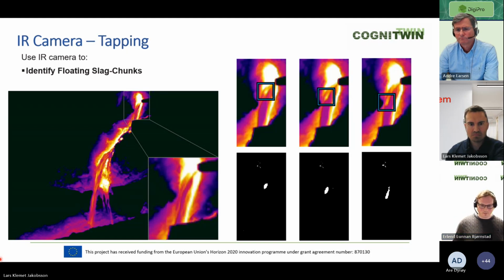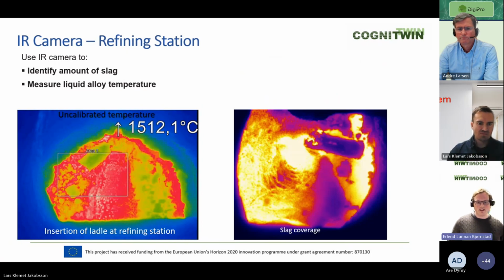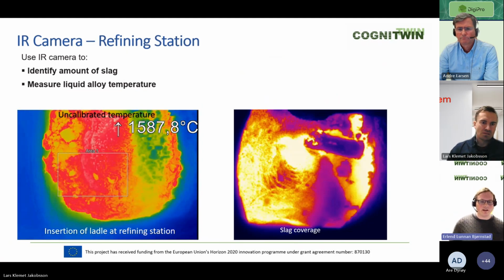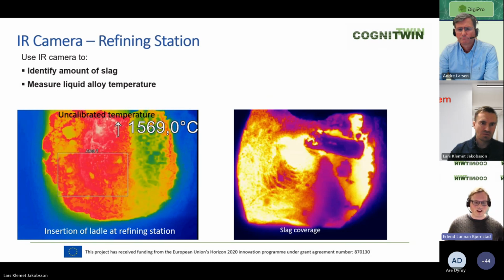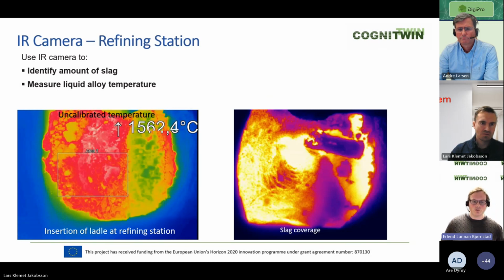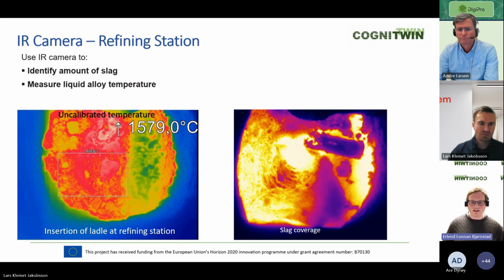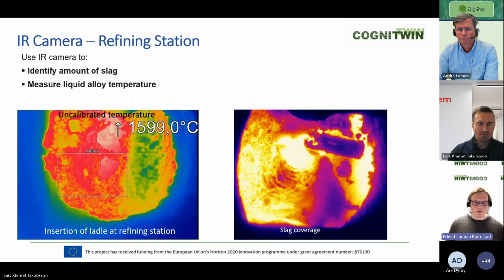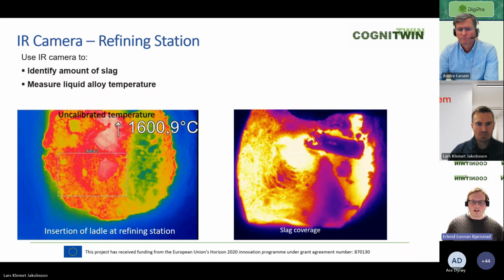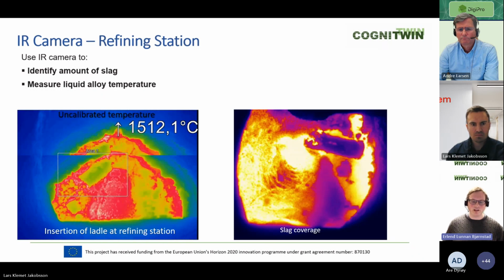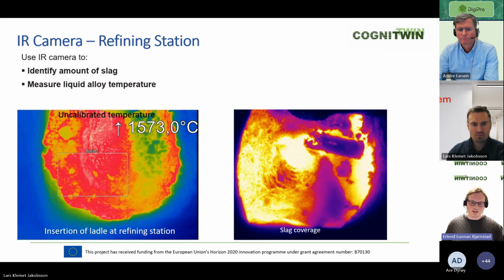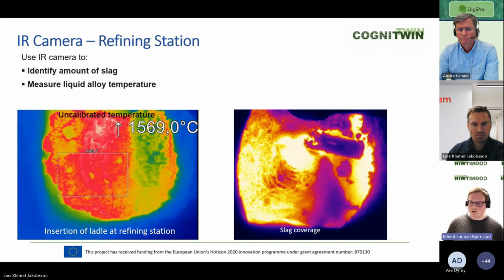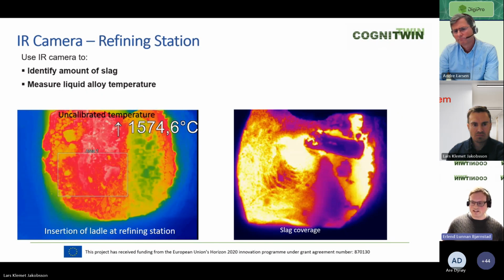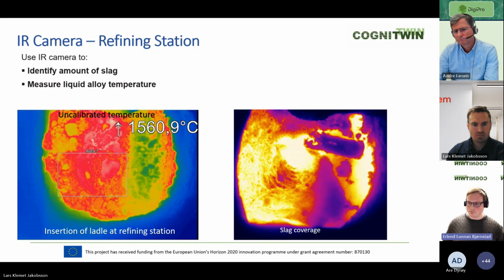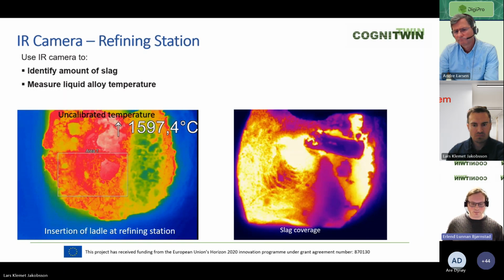Yeah, Lars? Yeah, so here we have a camera from the alloying and the refining station. Here we want to know the amount of floating slag on top. And then we want to see if we can measure and follow the liquid alloy temperature. We don't want the floating slag to be too thick, because if we alloy something that cannot penetrate that slag, then you will just burn it on top, which becomes really expensive very fast.